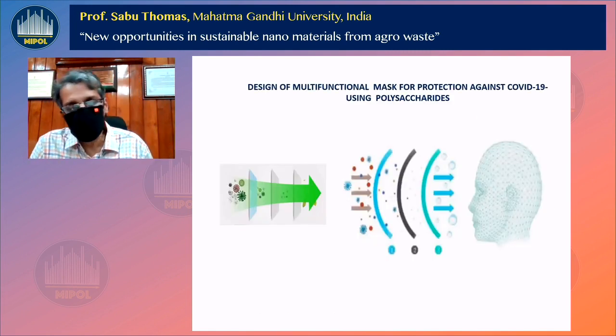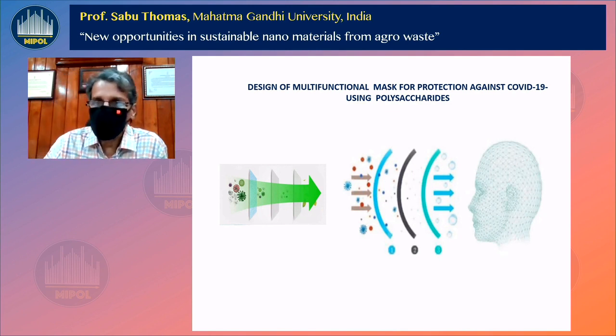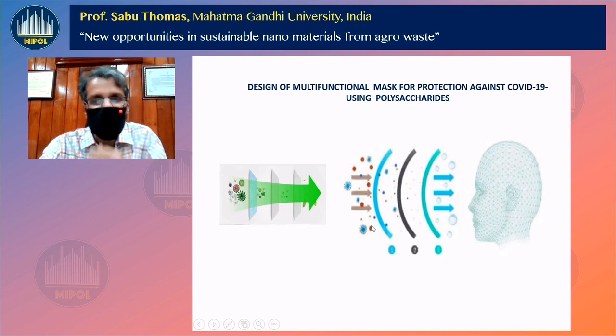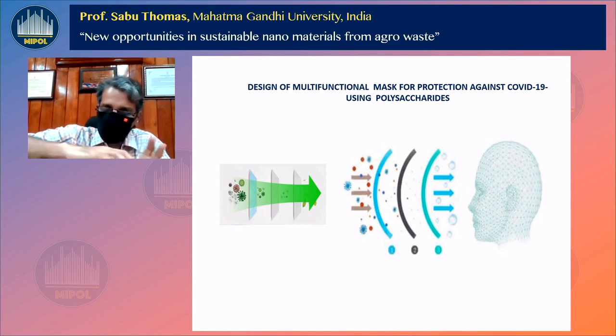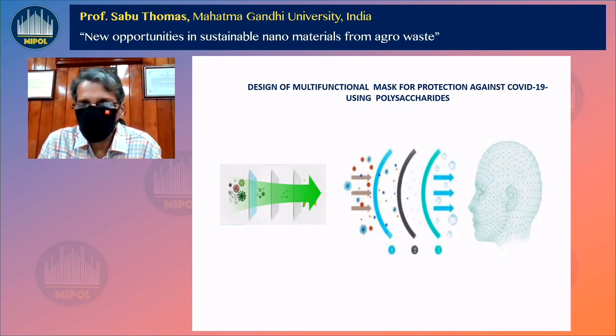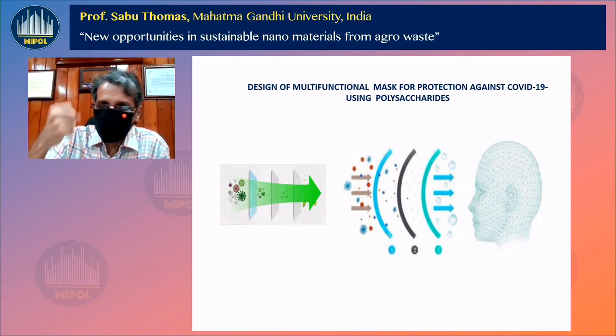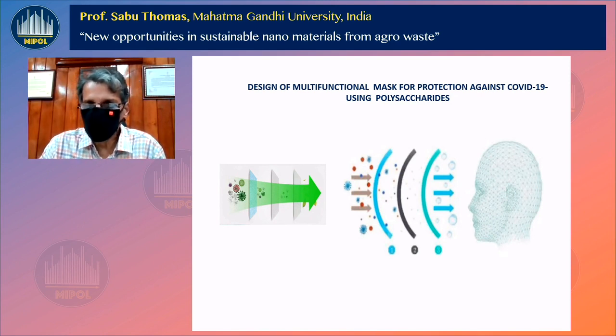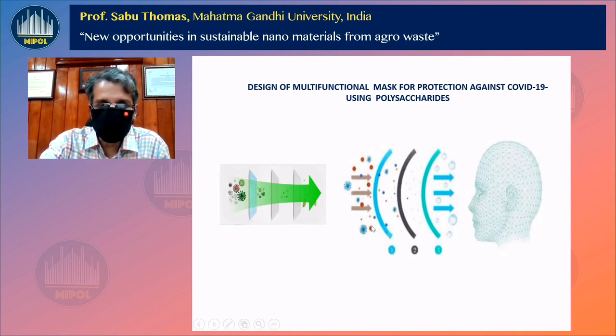Let me show you something we have done during the Corona time. We made an NSF program with the National Science Foundation in the US and many universities in India and Georgia Tech in Atlanta. What we proposed is a tri-layer mask. The outer layer is made of polyester coated with an anti-adhesive layer that can repel coronavirus because the surface is hydrophobic. The coating is an anti-adhesive polyelectrolyte.